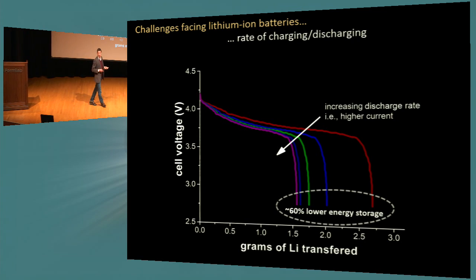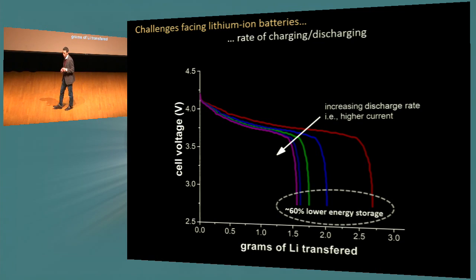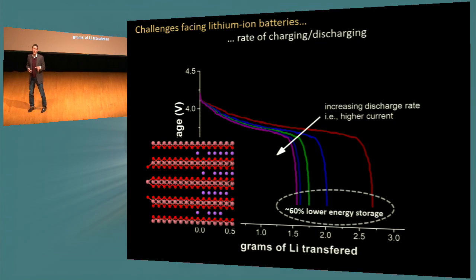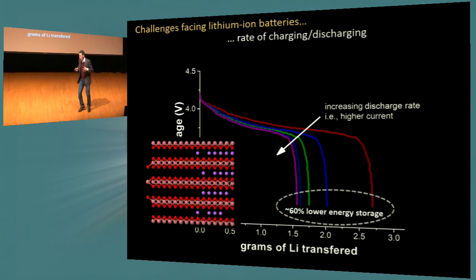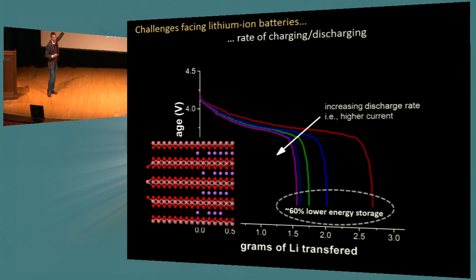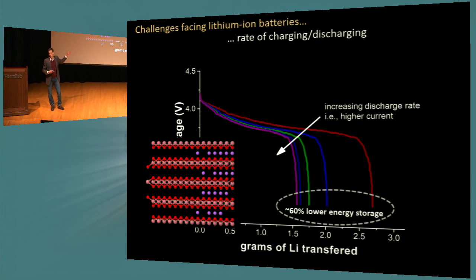What about wanting to charge your battery fast? Maybe a car, right? You fill it up with gasoline. It takes about two minutes to fill a car up. Maybe if you have a big truck, it may take four or five minutes. Well, you want to do the same. Well, that's a challenge. And we know why that's the case as well. Think about it. When you're running late to a plane and you're running through the airport as fast as you can, and you get to the plane and you basically stop at the doorway because everybody's trying to put their luggage up, trying to find their seats. The same thing happens to lithium. It can get to the material fast, but once it gets there, it kind of gets bottlenecked at the doorways, at the surfaces. And so you can see here, all that lithium kind of gets in there and stops and it doesn't let any more lithium come in. So you actually lose a little bit of capacity when you charge fast.